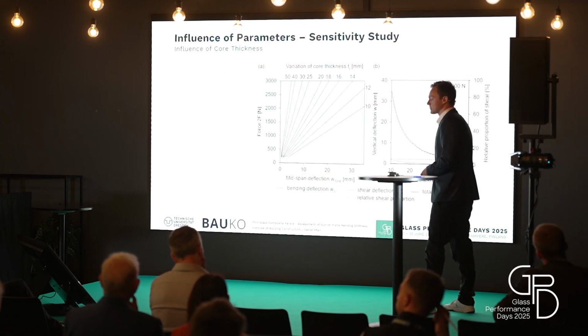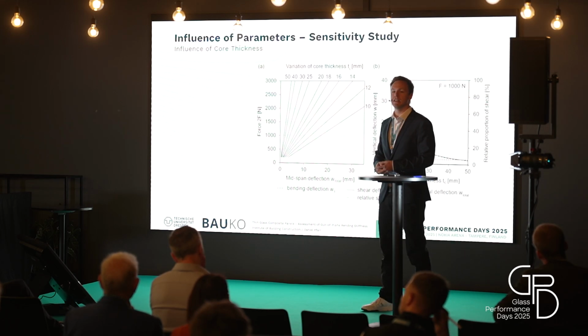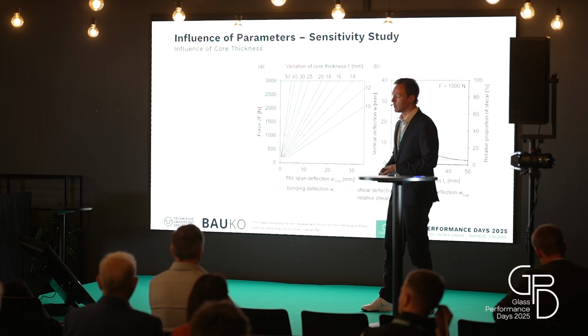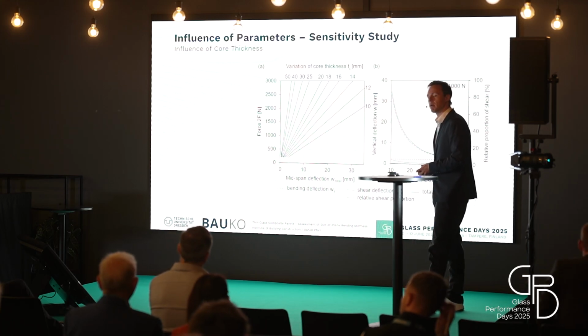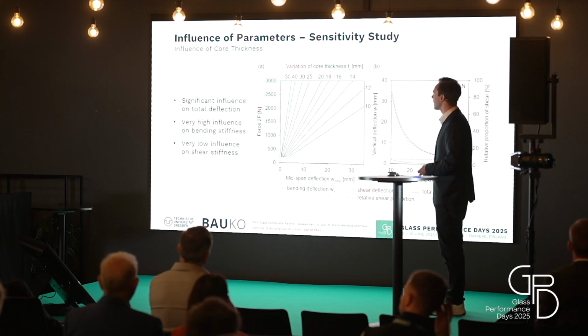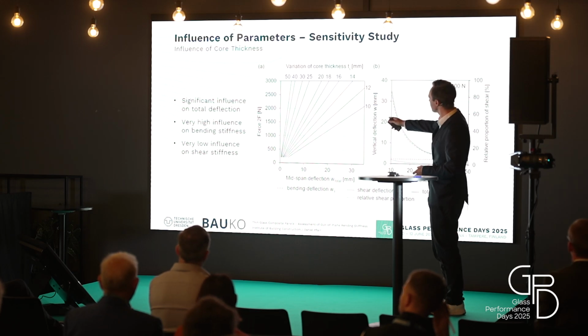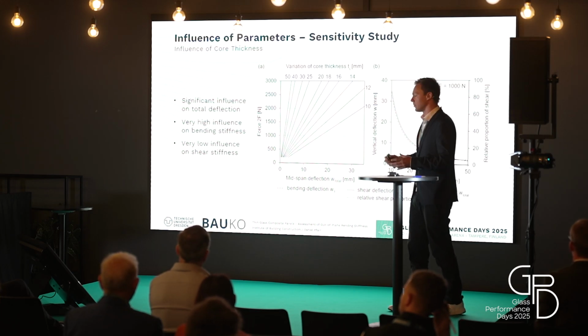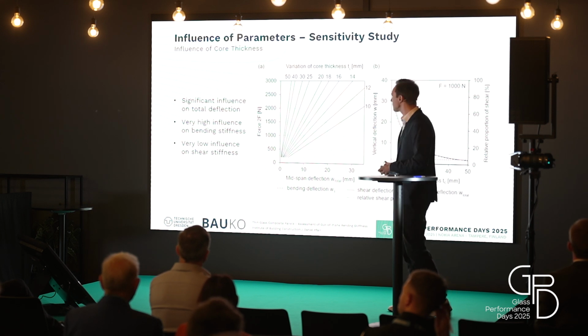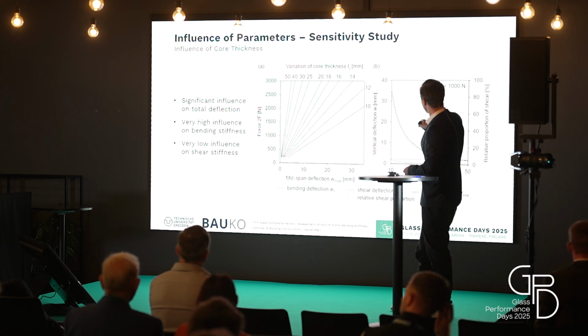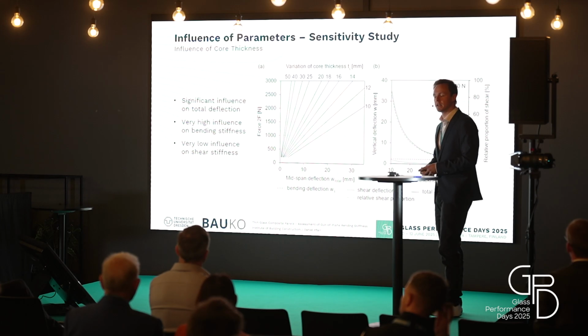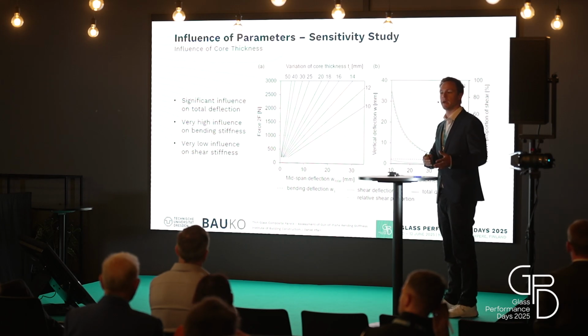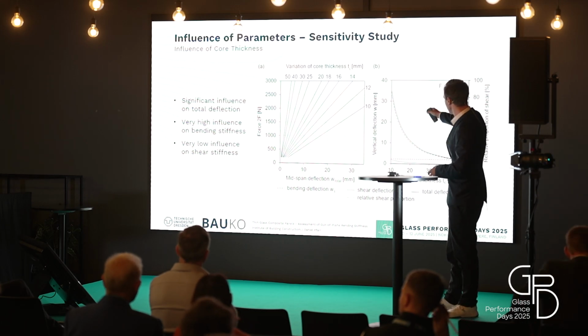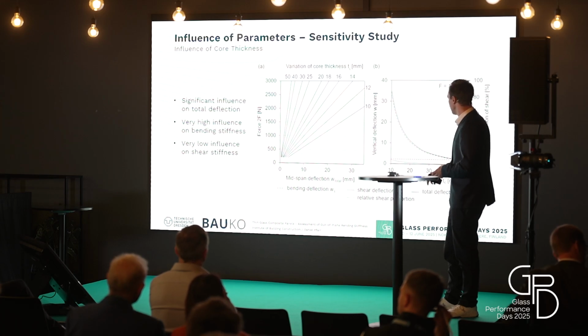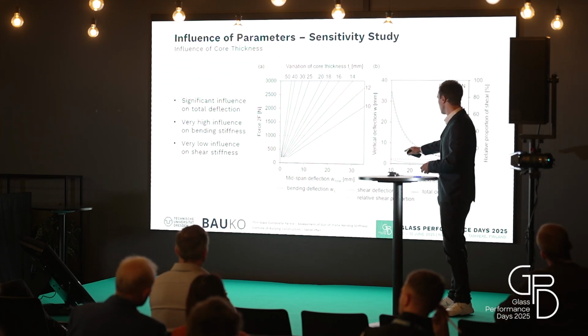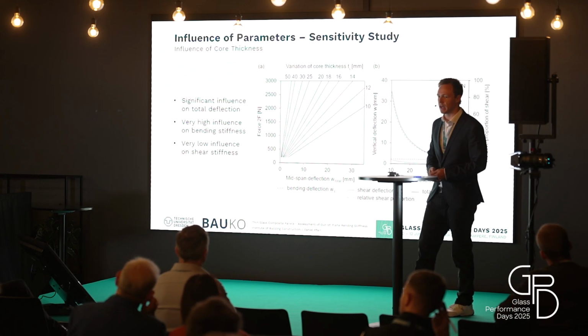Next, we have asked ourselves which parameter is actually influencing which part of the deflection. So we have 4 different parameters investigated. I would like to start with the core thickness. On the left-hand side, the diagram is showing you the total mid-span deflection over the force. And on the right-hand side, we can see the differentiation between bending deformation and shear deformation, again in dotted and dashed lines. And we have a relative shear proportion, which is interesting for us, as this colored red line.